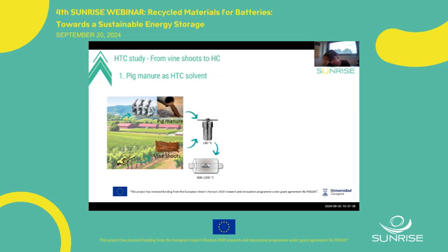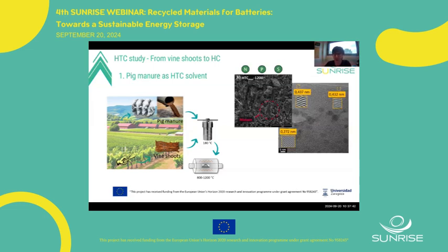To name some studies we have performed recently: we have studied how we can produce hard carbon from vine shoots, a residue from wine production, but using pig manure instead of water in the hydrothermal reactor, in order to recycle this residue, which of course has huge impacts on the environment, but also to introduce heteroatoms like nitrogen, phosphorus, and sulfur into the hard carbon. After performing these experiments, we obtained hard carbon with interesting morphologies, and also with high quantities of nitrogen, phosphorus, and sulfur that should improve the performance when used as anodes in sodium-ion batteries.